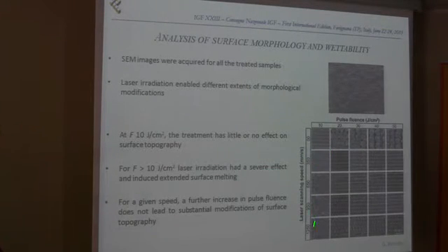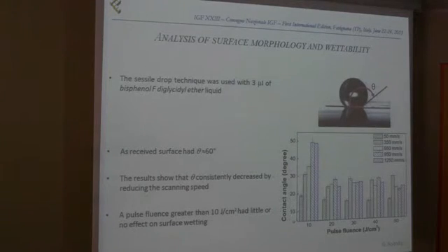So, as you can see, if we choose the pulse fluence of 10 joule over square centimeters, we don't see the effectiveness of the laser. Sometimes when we increase the scanning speed, we see like an effect of cleaning more than a really ablation of the surface. So we excluded these parameters to bond the samples, of course. From the other side, if we fix a scanning speed, like for example 650 millimeters per second, we can see that from 20 to 50 we are not able to realize the differences in the morphology within the different samples. And that's because the SEM itself alone cannot give us this information. So of course we had to go further and do further analysis.